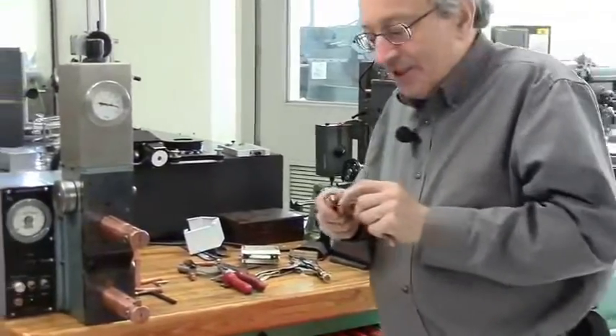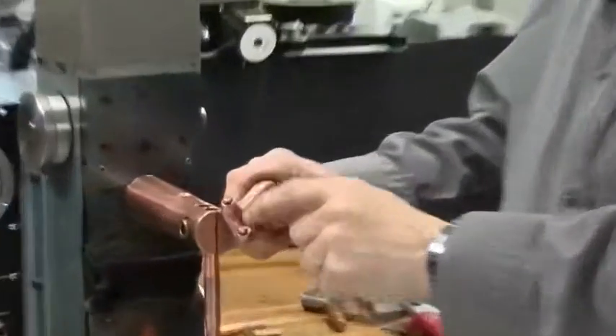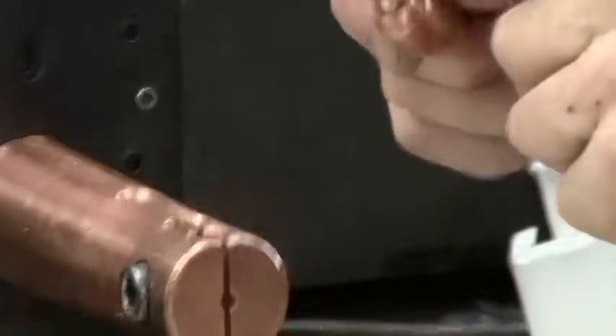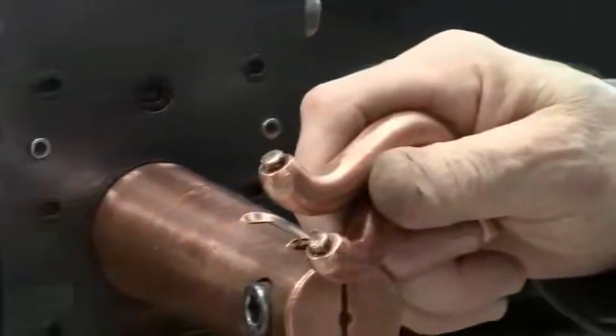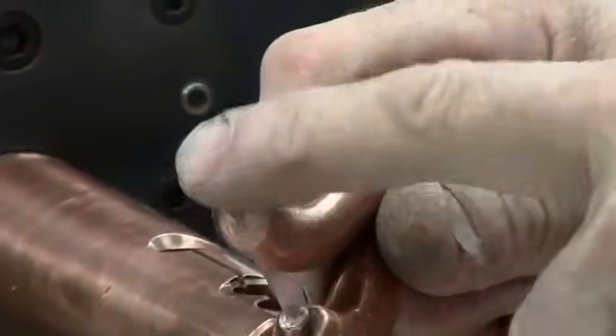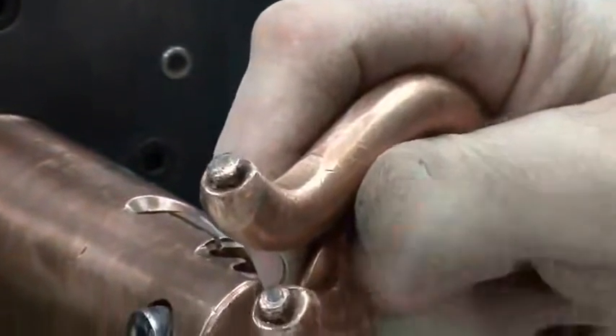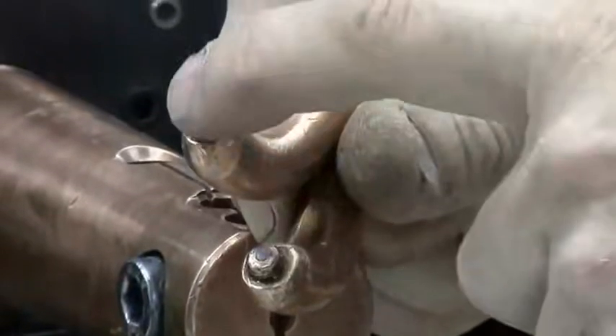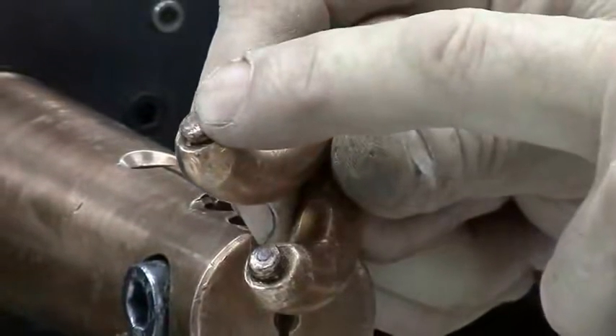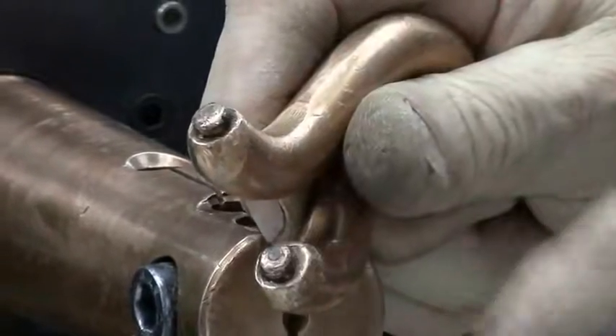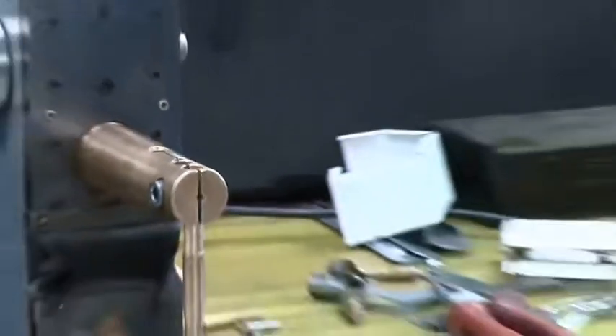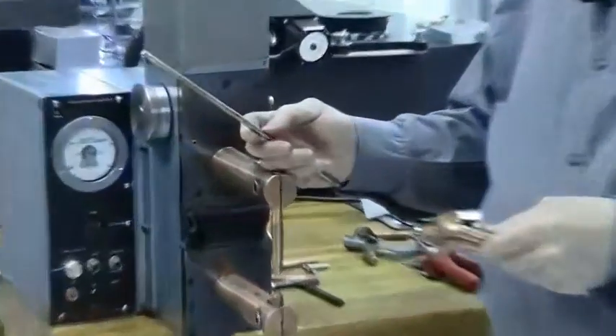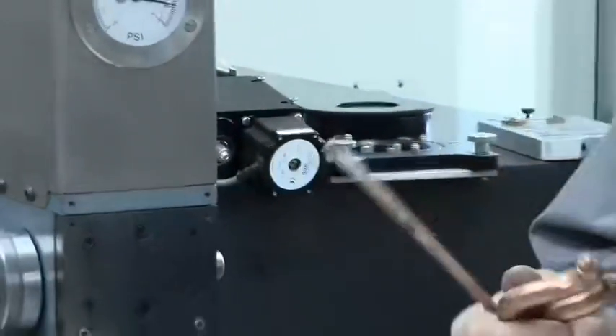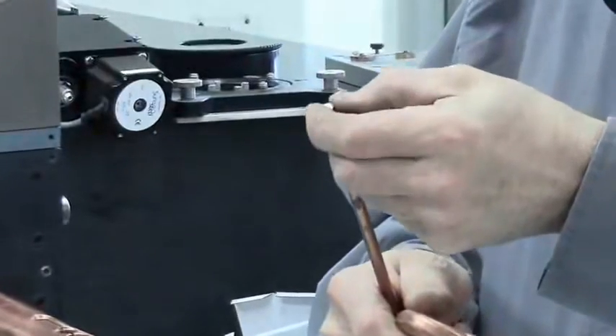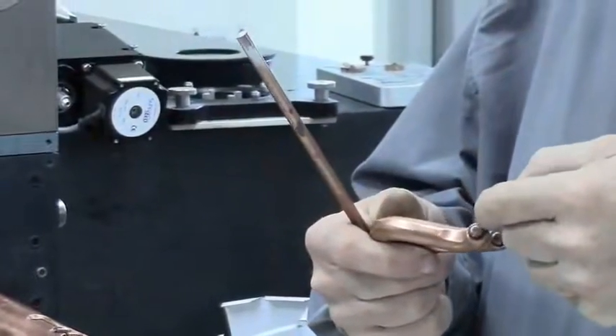Now, the tips of the electrodes are not made of copper, although you can use copper. You can just leave the metal itself as a tip, but this tip will easily squeeze and wear because copper is a bit soft. So if you want long-lasting tips, you have to insert tips, and these are made from either copper tungsten alloy or copper chrome alloy. The cheapest is copper chrome alloy. You buy a rod like this. You can get it from McMaster-Carr. It's cheap, and this will last you for 100 tips. A good way to machine it is a bit of taper. Make a taper hole, press it in.